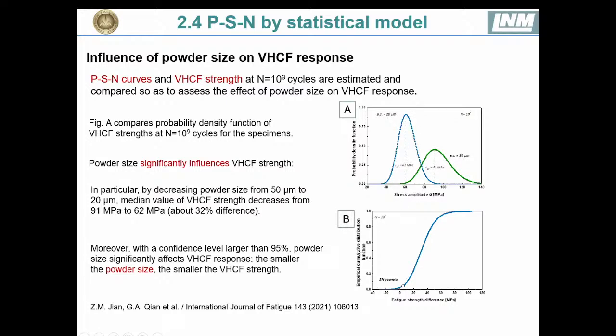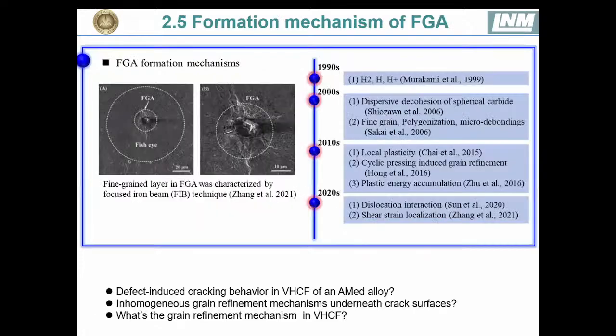And also with this method, we can obtain the result of fatigue cumulative failure probability with fatigue strength. And we can see that as fatigue strength increases, the failure probability also increases. This is also in agreement with our common practice. And then in the next part, we will discuss the crack initiation mechanism.